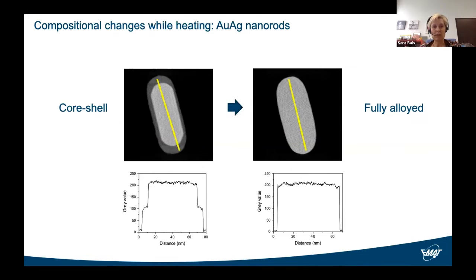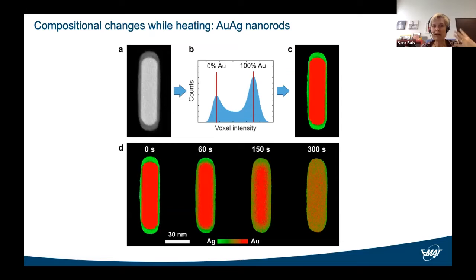To investigate this in more detail, we're going to be performing a quantification procedure based on this Z contrast imaging. So in A, you see a slice through a three-dimensional reconstruction obtained at room temperature. And if we look at the distribution of the voxel intensities, you see two peaks, one for gold and one for silver. Now, if we start heating and if we start collecting three-dimensional reconstructions, it is a fair assumption to state that every voxel in one and the same particle should always be a linear combination of the gold and the silver intensity. So this is what is illustrated by these color codes at the bottom.